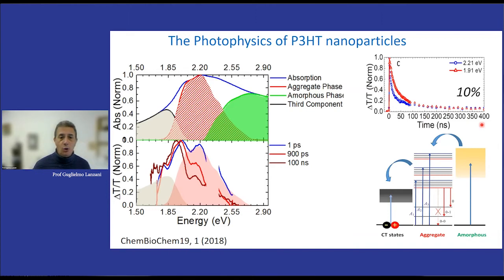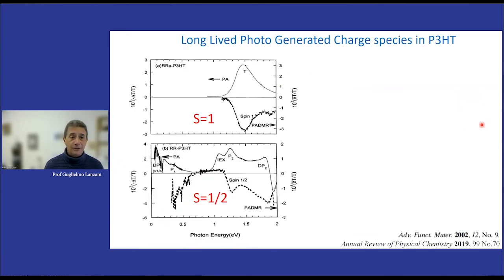So they can be triplet states or charged states, say charged carriers. And then we look back at the experiment done by the group of Vardeny in Utah. You see, he was comparing the amorphous regiorandom polymer to the regioregular crystalline polymer, and he was able to measure the spin of the long-lived excitation. Now, without going into detail, I'll tell you that from this experiment with the magnetic field, he could conclude that in the amorphous part, there are mainly triplet states surviving on the long time scale, while in the crystalline part, which is the one that we are effectively exciting, there are only charged states surviving, spin one half.